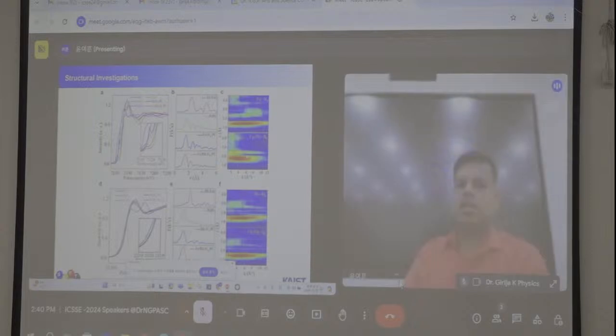We also look at the oxidation states. Usually the pink one is the metallic state, which is zero oxidation state. When the metal oxidation state increases, it goes in the positive direction. So further we also compare with the single atom and the dual atoms. You can see dual atom gets additional peaks, but in case of single atom there is none. Then we may conclude that rhodium is nearly bonded with the iron, but not much affected by the metal nanoparticles. And rhodium also gets a similar observation like iron.